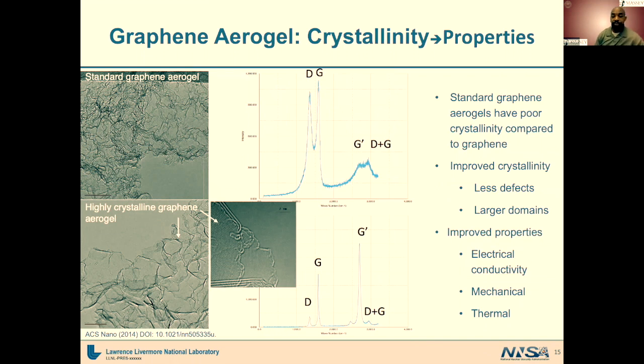Another way in which you can really control the properties, which I alluded to, is the crystallinity of your aerogels. So here is showing transmission electron microscopy and Raman spectroscopy for our graphene aerogels. As you can see from the TEM, the sheets are clearly very wrinkly with lots of curves, which suggests a fair amount of defects. And then if you look at the Raman spectra, that's really confirmed in that you're seeing a large D peak, which is indicative of defects. And the large full width half max here also points to fairly small domains as well.